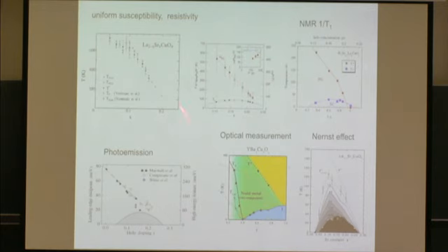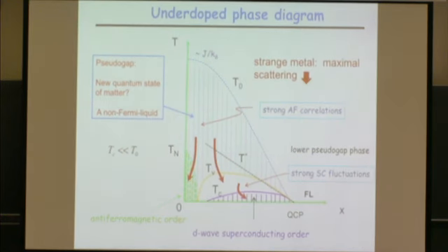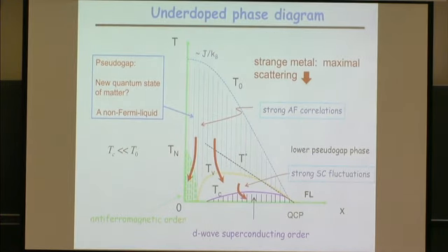This is probably the highest one, and the Nernst effect actually happens up to about 2 times Tc, at a different temperature scale. Nonetheless, it tells us some universal behavior for all these cuprate materials, which can be summarized as follows. Here the axis is some kind of charge doping concentration, and in the undoped regime, you have a long-range antiferromagnetic ordering state, and at finite doping, you will have a